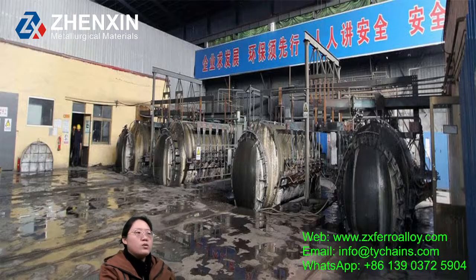Ferronickel's nickel content is between 10% and 40%, and there are different grades, mainly defined by the nickel content and the impurities. For example, Ferronickel 10 means 10% nickel, Ferronickel 20 means 20% nickel, and Ferronickel 30 means 30% nickel. Ferronickel 10 actually has a nickel content between 8% and 12%, and it's suitable for low nickel alloy steel and foundry applications.